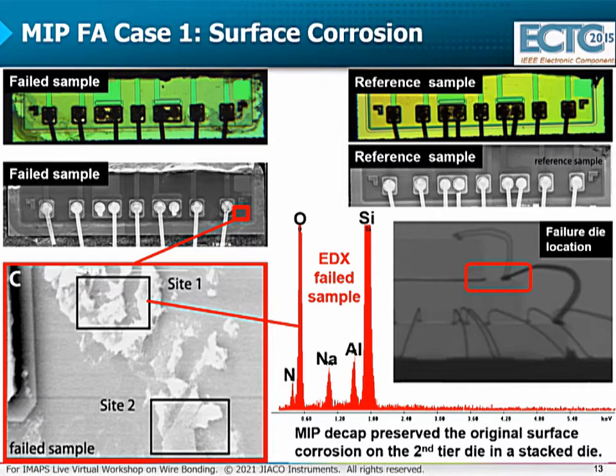The challenge with acid and also CF4-containing plasma methods in this particular FA case study is that the contaminant and/or the surface of the die are being etched, and that actually destroys the evidence.